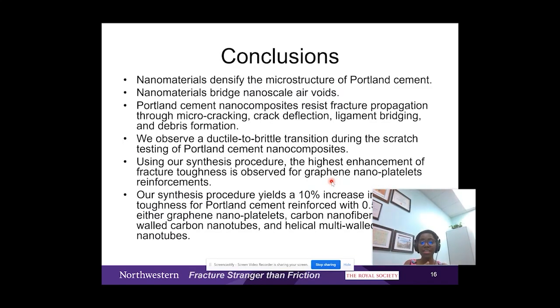So in conclusion, I've shown that nanomaterials yield a decrease in the microporosity and in the size of micropores within Portland cement. I've shown that nanomaterials bridge nanoscale air voids. I've shown that scratch tests can be used to probe the fracture toughness of Portland cement. And in the case of cement reinforced with 0.5% of nanomaterials, we see an improvement in the fracture toughness by up to 10%. Thank you very much.